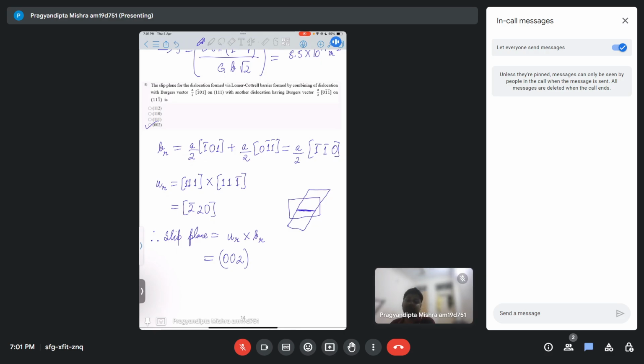Okay, so this is how you can solve a problem. First you add the Burgers vectors, then you find the line at which these two dislocations will intersect. That can be found by taking the plane normals of both the planes and then finding the cross product, as the dislocation line will be perpendicular to both of these plane normals. Once you know that, the slip plane would just be the cross product of the dislocation line and the Burgers vector.